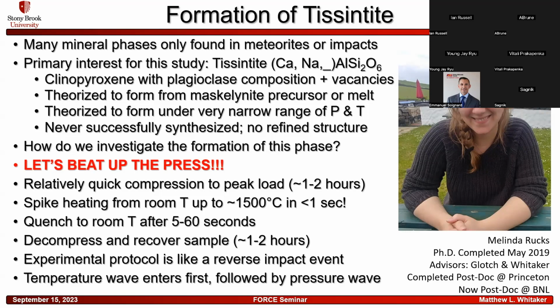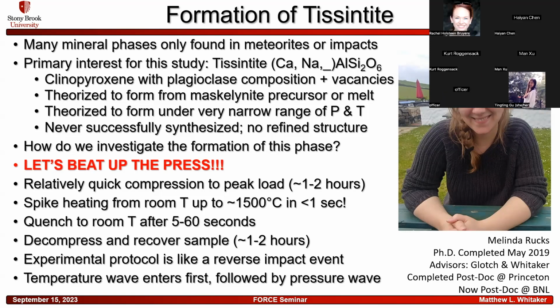Whereas in an actual impact event, you see a pressure wave that comes in and enters the sample. And that pressure wave is followed by a temperature wave of heating that comes behind it. In this case, what we're doing is we have a sample that's confined under high pressure, and we send in a temperature wave, and then the thermal expansion of the materials in there causes the pressure wave to follow it. So in a sense, it just happens in the exact reverse order that you would see in a natural impact.